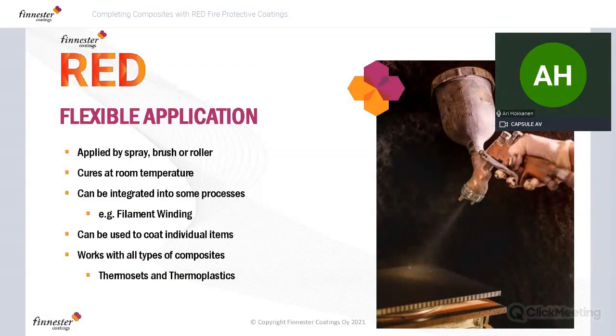We found that it's also quite compatible with some composite processes. At the moment, filament winding is quite an interesting topic for us. We have a commercial business where the coating has been incorporated into the existing filament winding production process, coating individual items, and also we're finding that we can work with both thermosets and thermoplastics. So it's not a case of just sticking to perhaps an epoxy glass fiber composite or polyester glass fiber. It's very broad in its application, this technology.